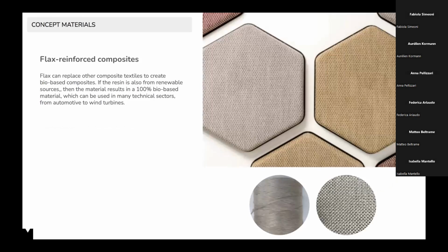In terms of composites, an interesting area is that of flax reinforced composites, or flax or hemp or other natural fibers that have very good performances in terms of mechanical resistance. If combined with either fully or partly bio-based resins, they would create reinforced composites that would have a very high percentage of bio-based raw material, reducing significantly the carbon footprint. In some cases, flax also manages to be lighter than standard composite textiles like carbon fiber or glass fiber, and it has been already used quite broadly in automotive.